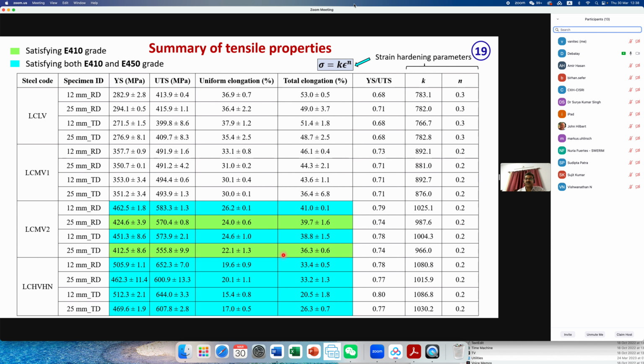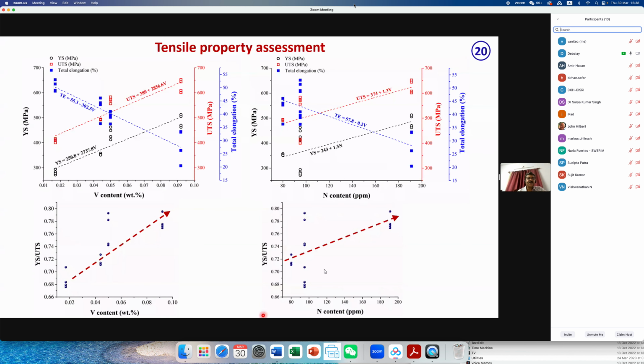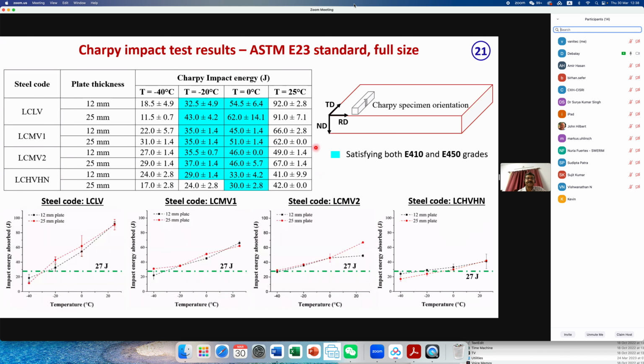Elongation is quite good. So you can see the typical results of the tensile properties listed here. We are seeing typically with increasing vanadium content, as expected, strength, YS, UTS goes up, a little bit of negative effect on elongation. Similarly, nitrogen. So we have found more or less similar effect with the data point that we have from this project data. YS, UTS level also we have found slightly going up with the vanadium and nitrogen content.